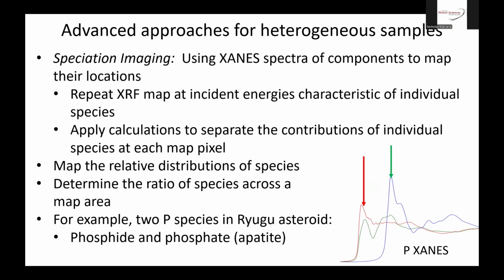Okay, and just to finish up, the last subject here is just some advanced approaches for heterogeneous samples. The first one is speciation imaging, where instead of looking at differences in the emission spectra, using the XANES spectra of the components that are in a mixture to map the distribution of those components. For example, in phosphorus, if you make one map at this energy and one map at this energy, then you can do some math and separate the contributions of each individual component to each pixel of a map. And so that's kind of a neat way of mapping the relative distribution of different species. And then integrated over an area of a map, you can then determine the ratio of those species within the map area.